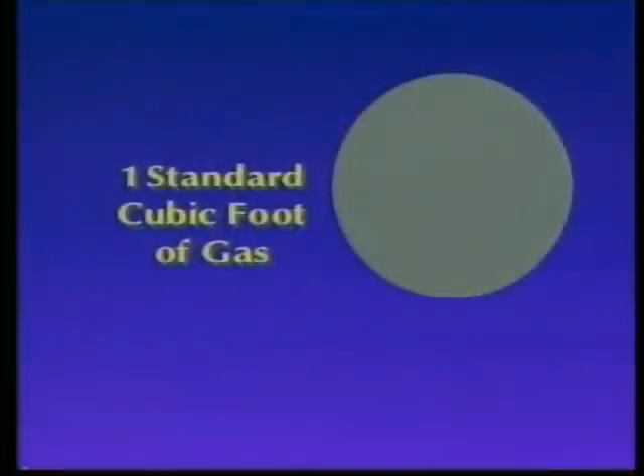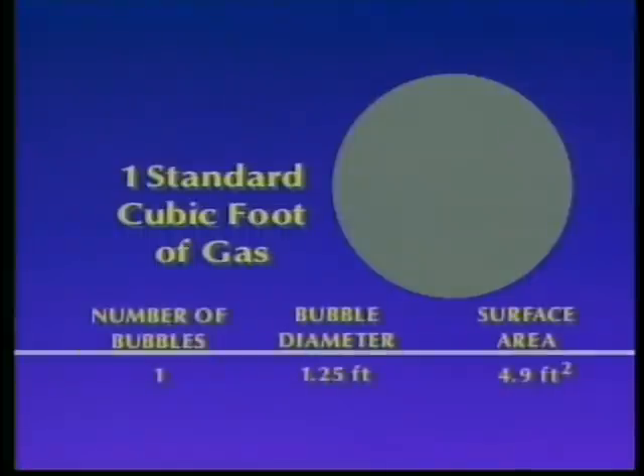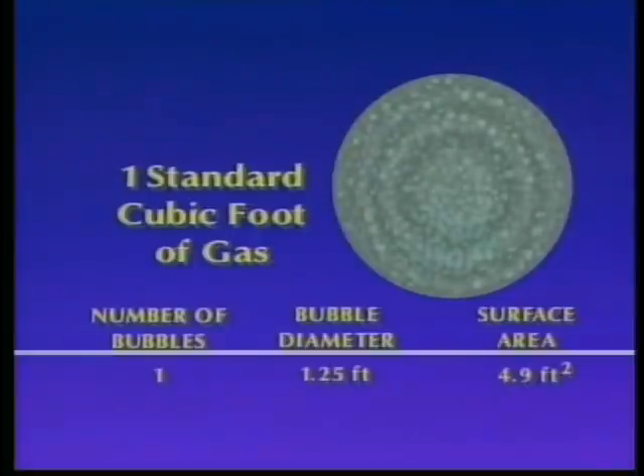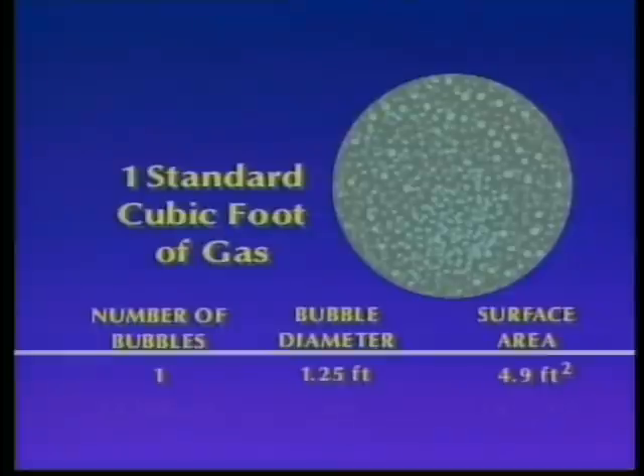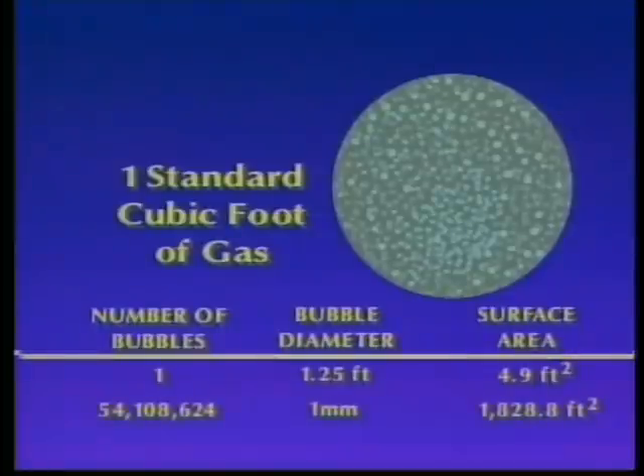To be able to demonstrate the quantity of surface area that's capable of being developed by decreasing bubble size, I'll refer to this pictorial wherein we have 1 standard cubic foot of gas. As a perfect sphere, that would constitute a diameter of 1.25 feet and a surface area of just under 5 square feet. On the other hand, if we were to take that same volume of gas and generate bubbles of 1 millimeter in diameter, the amount of surface area generated with that same volume of gas would be in excess of 1,800 square feet of surface area, wherein there'd be 54 million bubbles produced of that diameter.